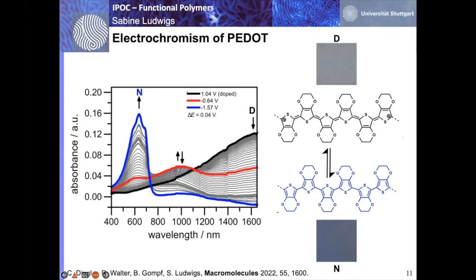If you do that scientifically more in depth with absorption spectroscopy, then you see the absorption as a function of wavelength. In black is the doped material, with absorption in the NIR. When you de-dope the material, you have an intermediate state which has the red absorption curve, and in the neutral state it shows this blue absorption curve, which I highlight here also with the potential. So minus 1.57 volt means that the polymer is completely in its undoped, neutral form, whereas at plus 1.04 volt, it's fully doped. And we can switch between these two states.